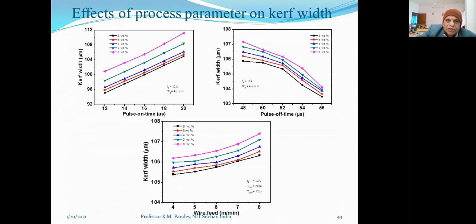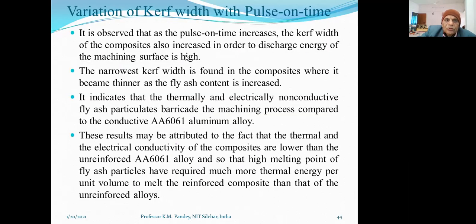So here is the effect of process parameters on kerf width. Again, on the x-axis we can see pulse on time in microseconds, and kerf width in micrometers is given on the y-axis. So this is the variation of kerf width with pulse on time. It is observed that as the pulse on time increases, the kerf width of the composite also increases, because the discharge energy on the machining surface is high.